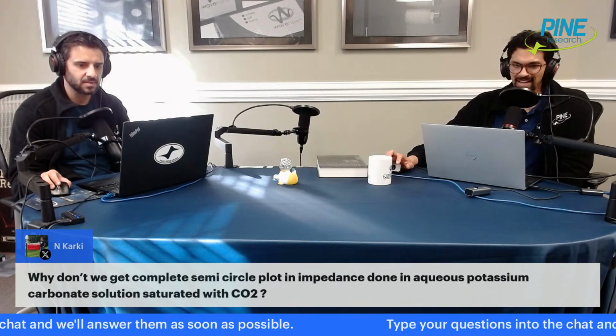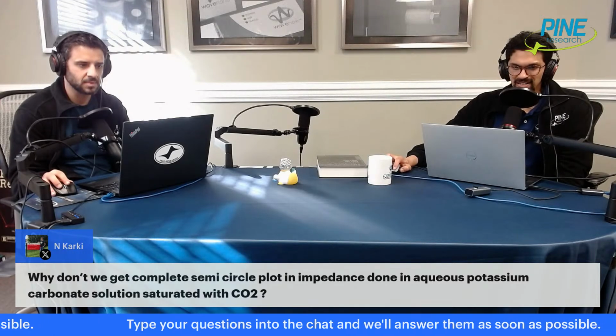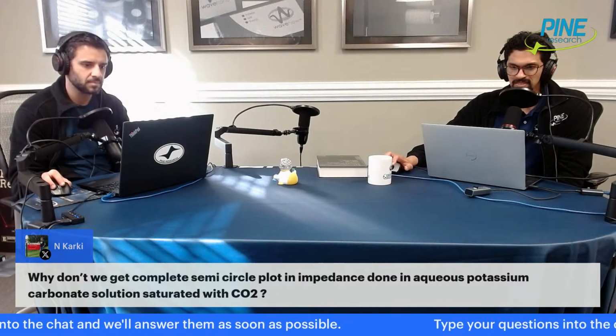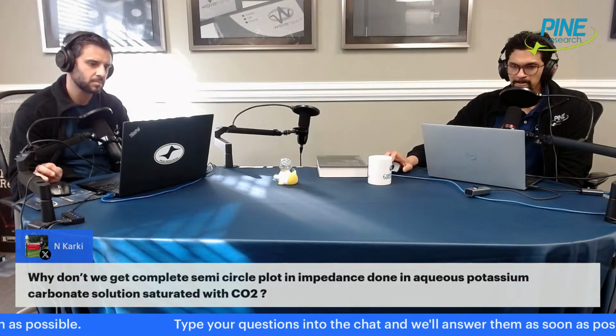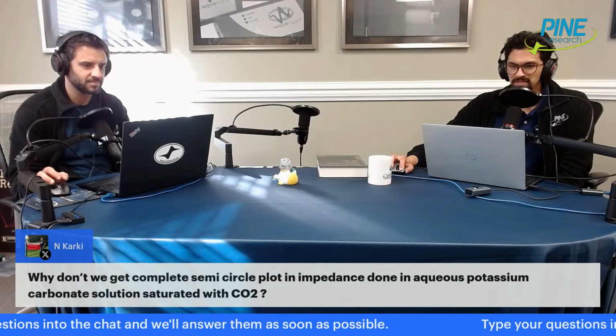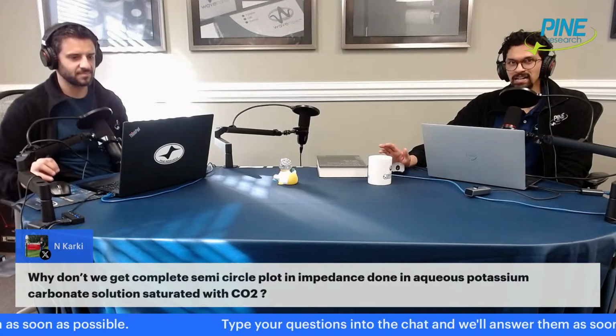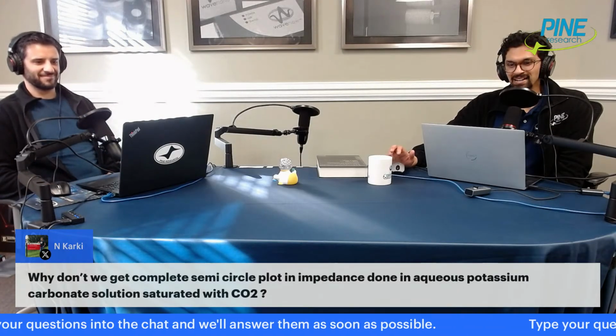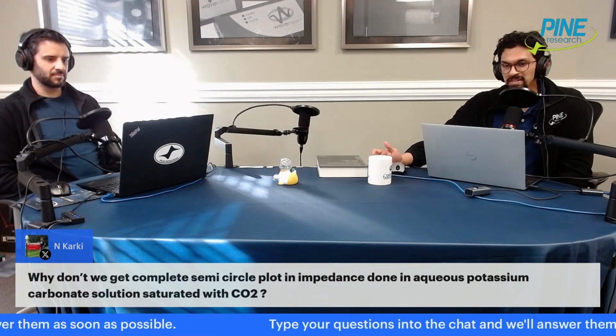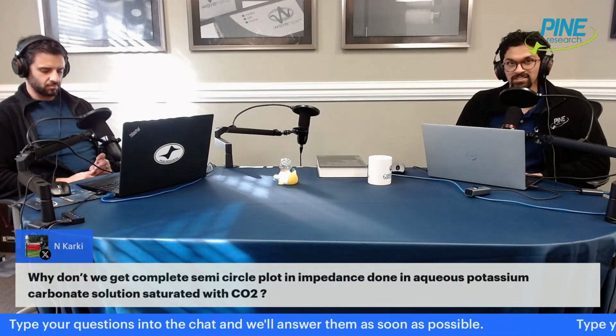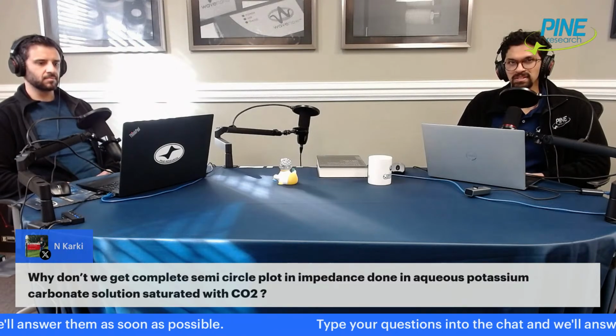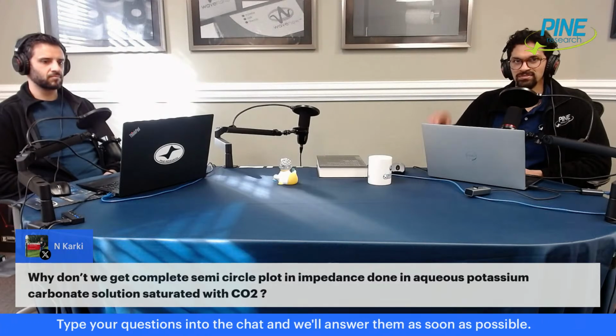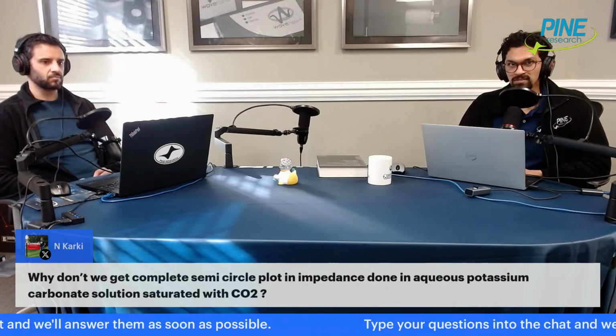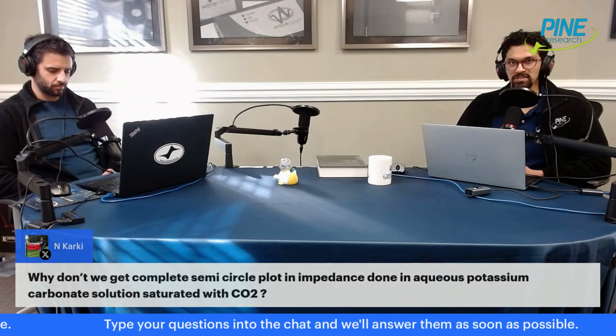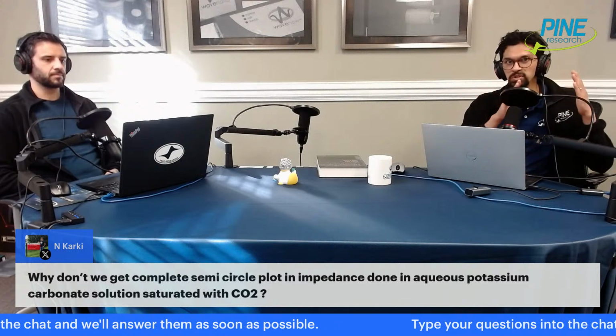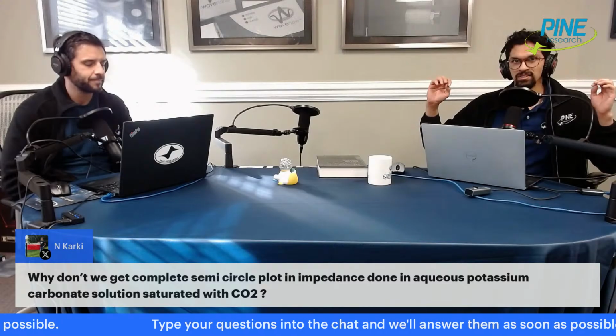All right, we have a question finally. We got to this one. Yes, from X. I know you're probably not there right now, but maybe you'll watch this later. Why don't we get a complete semicircle plot in impedance done in aqueous potassium carbonate solution saturated with CO2? I think this is another one of your potential triggering points. One thing that might be happening is you are doing EIS at a potential where nothing is happening. If you just have potassium carbonate at OCP saturated with CO2, and no redox reactions are occurring, you probably won't get a semicircle. If you look at EIS around the E naught of a one electron reversible redox pair, that's when you'll get a semicircle and a Warburg diffusional tail. But if you move away from the E naught, that semicircle will start to disappear.